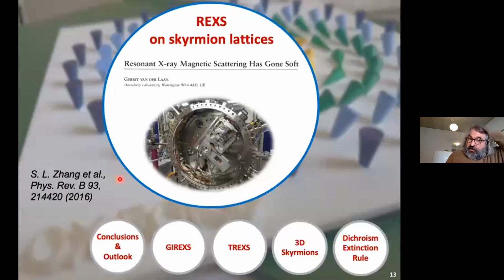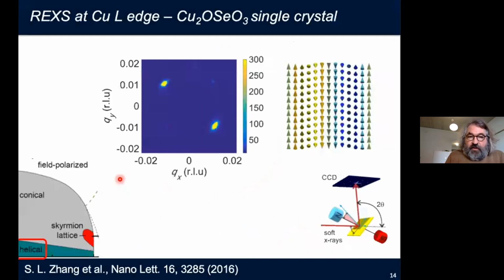Okay, so how do we look at skyrmions? We are using resonant elastic X-ray scattering in the soft X-ray regime. First of all, we do what everyone does with a real space imaging technique, but in reciprocal space. So this is the diffraction pattern in the helical state. You can see 2 Friedel pairs, in fact, one that you should be seeing quite easily, and then a much fainter one. So what this is, is 2 helical domains in the system, which you obtain at 0 or low field.